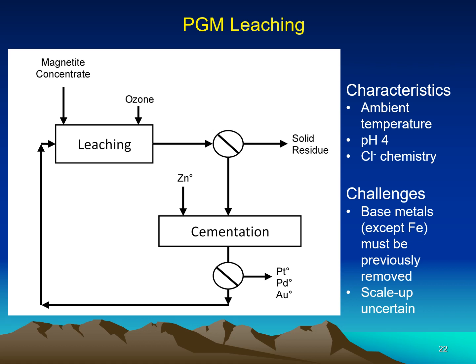The characteristics: ambient temperature, pH 4, chloride chemistry. So here in the cementation, we don't have a problem with chloride. The challenges are base metals must be previously removed, except for iron, because the iron goes to hematite, which is a solid. It stays in the residue. And the scale up right now is uncertain.